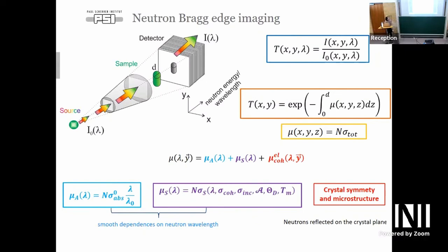That Y you have there is like an orientation. Yes, exactly. That depends on how the beam is coming through your material. The other components are not depending on that. They are completely independent of the orientation. If you have a uniform sample, in the sense that your material is the same, not the crystalline way, same atoms, just differently arranged, these two components depend just on the type of elements that you have in your structure, not the crystal structure itself.